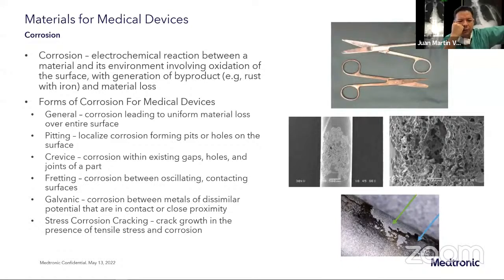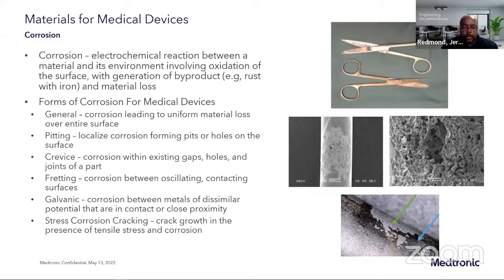Gerald, so the galvanic corrosion, the most common example in clinical practice will be to connect a titanium implant with a stainless steel implant. Is that correct? Yeah, that's where you start to get a little bit of a difference in the galvanic potential. And so I think in a spinal application, we do want to try to avoid those types of interactions. The biggest difference where you have a significant potential for galvanic is when you pair a more noble metal, noble metals being metals that do not corrode, like gold or platinum, with something that is a less noble material, like aluminum. That's where you'd have a really high potential for acceleration of a corrosion reaction due to galvanic.